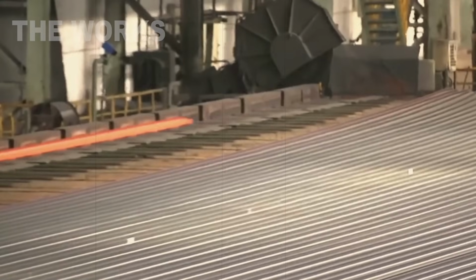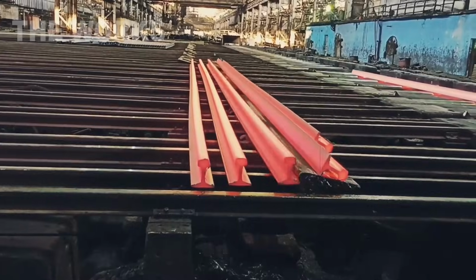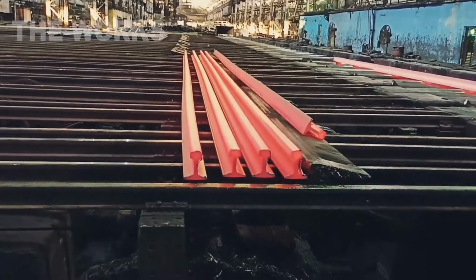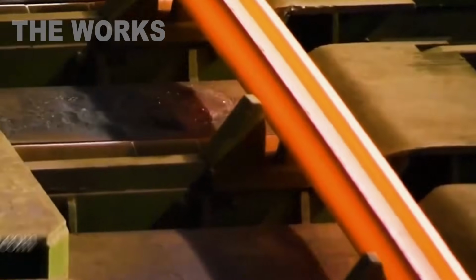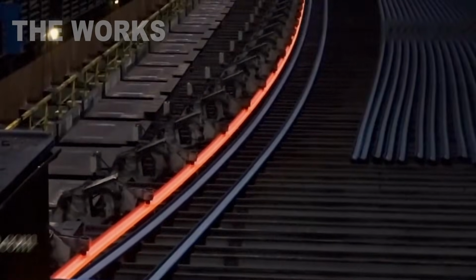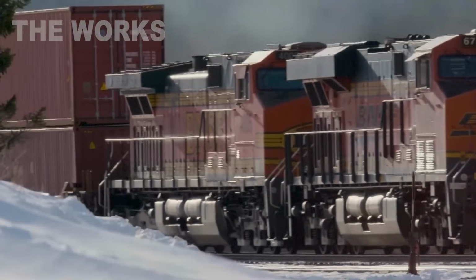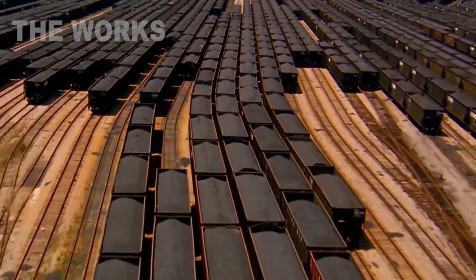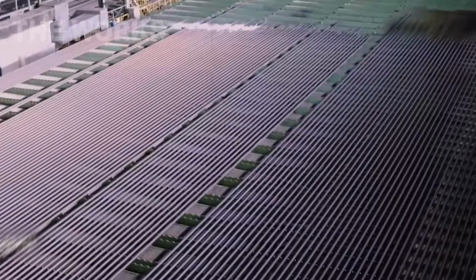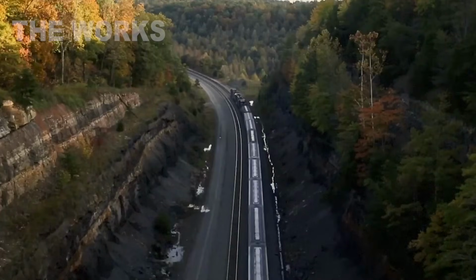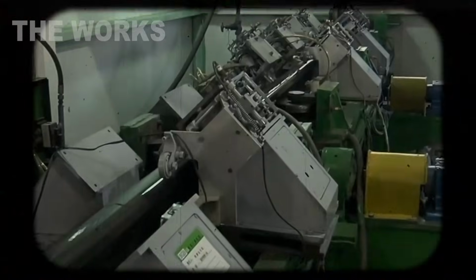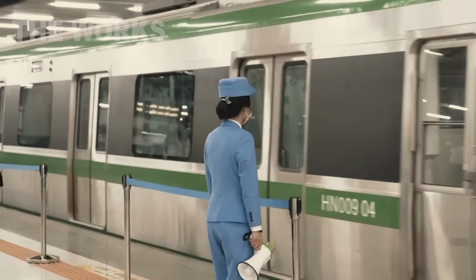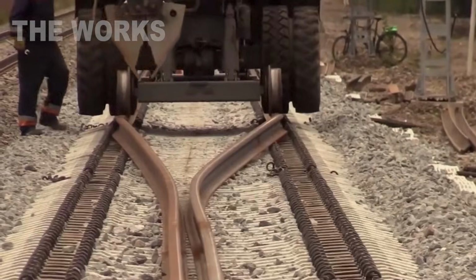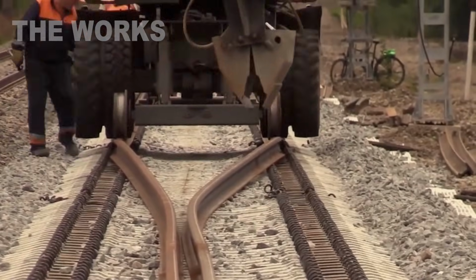But to avoid brittleness, the rail is slowly heated and cooled again. This balances the structure, relieves excess internal stresses, and ensures that the rail will withstand both frost and heat, and thousands of trains a day. As a result, the metal holds its shape and withstands a pressure of tens of tons per square inch without deforming. Before the rail hits the road, it goes through a whole series of rigorous tests, as if it wants to join the army of high-speed transport.